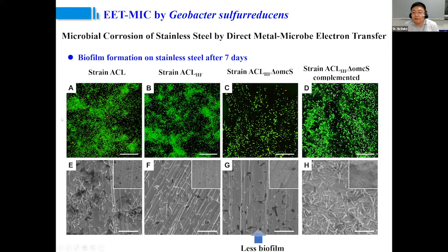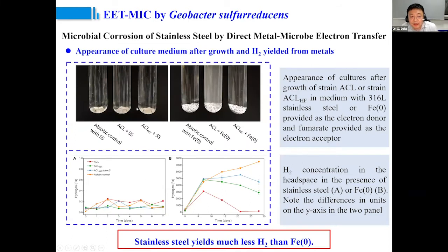So this is the biofilm morphology, and based on the hydrogen measurement, when we use stainless steel, there is almost no hydrogen produced. First of all, the OCP cannot satisfy the thermodynamics for cathodic hydrogen evolution. And if we use zero-valent iron, it will produce a lot of hydrogen. So based on this, we eliminate the influence of hydrogenase by using stainless steel and deleting the hydrogenase genes.